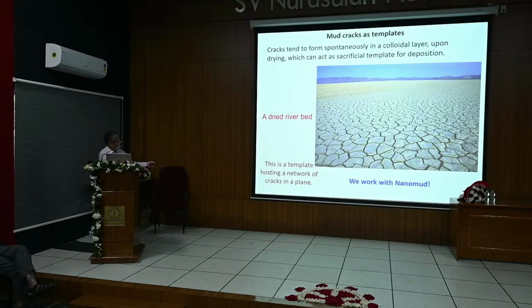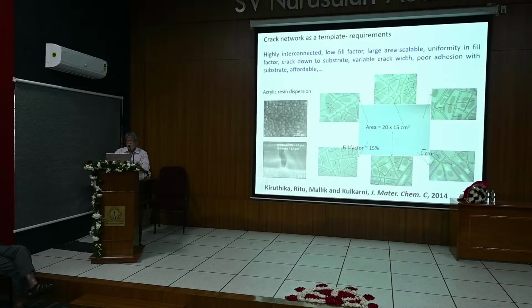Just that we don't use the ordinary mud, but in the lab we make nano mud, a very, very fine particulate system in a given solvent. And when we disperse it as a thin film, thickness could be of the order of only a few hundred nanometers, and that dries up producing fine cracks. These are the particles we use. These are readily available, inexpensive acrylic resin particles, and there are a lot of reasons why it behaves so and all that. I'll not get into that.